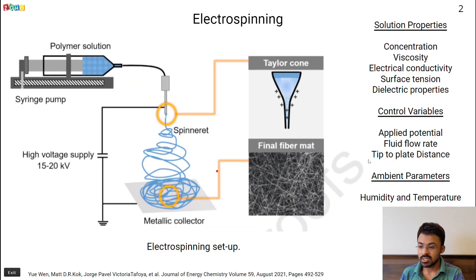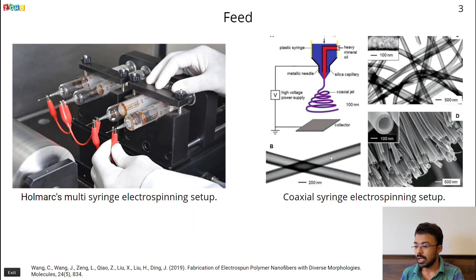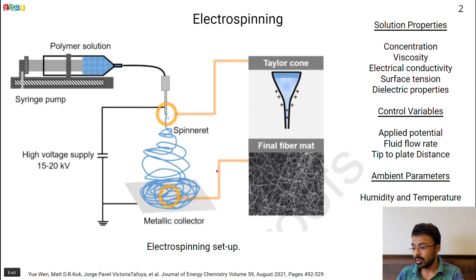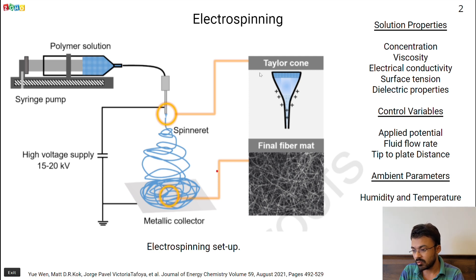The manufacturing process I will be discussing today is electrospinning. In electrospinning there are three main components: the syringe pump, the spinneret, and the metal collector. The syringe pump loads the polymer solution into the spinneret and a pendant drop is created. When we give a positive bias to the spinneret and a negative bias to the metal collector, the metal collector attracts the pendant drop and a Taylor cone is generated, through which a jet is formed and collected on the fiber mat.